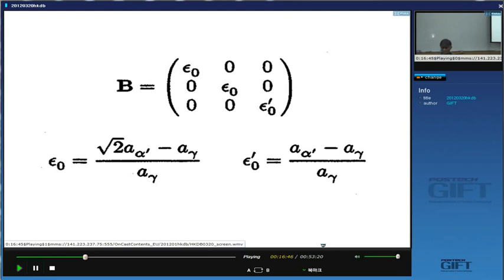So if in the same steel you see slightly different orientations, that cannot be because the martensite is adopting different orientation relationships, because it only depends on the lattice parameters. There must be some other factor that's influencing changes in orientation, and more than likely the austenite does not have a uniform orientation. So if you do EBSD on austenite, you will find gradients of orientation in the austenite.